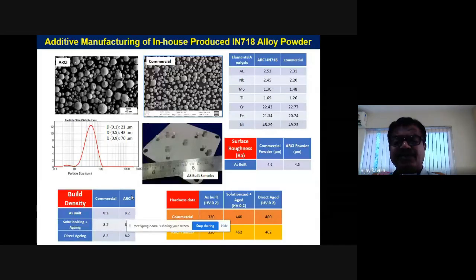And IN718, so these are all the powders. You can see our ARCI powder and the commercial powders, and we could compare the chemical analysis. It's all comparable to the commercially available, and even the surface roughness. The AM coupons were built to evaluate it, and these are also comparable. Looking at the hardness data with density, the hardness is also comparable, and the solutionized and aged are also comparable to the commercially available powder. That means we have successfully made the powders for additive manufacturing.